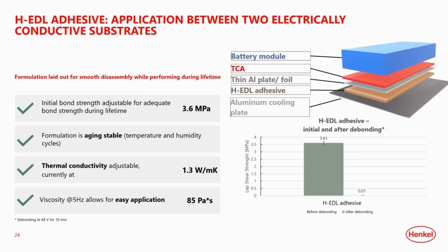Thermal conductivity of the thermally conductive adhesive is something that can be adjusted depending on the performance requirements, and it's currently at about 1.3 watts per meter Kelvin. And of course, the materials have been tested to the same typical aging and stability standards that we use in other typical automotive applications, such as heat and humidity aging and cycling.